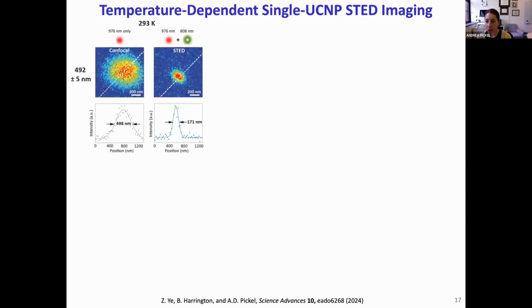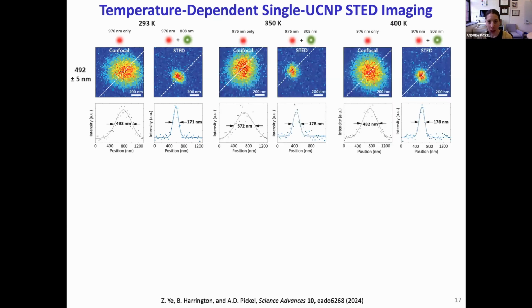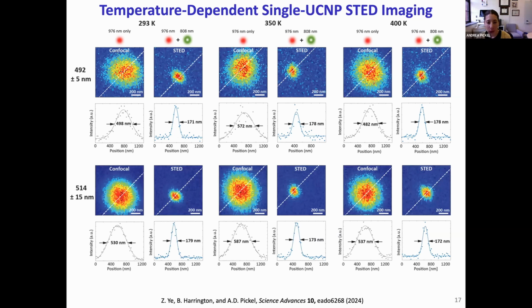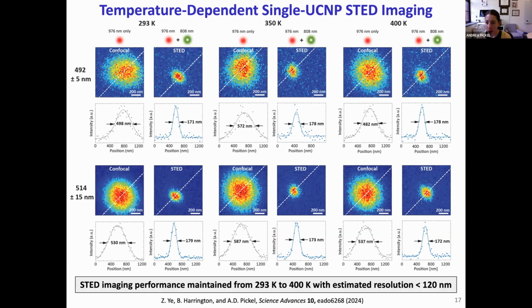From the spectroscopy results I just showed, we now know that we need to test our ability to maintain similar imaging resolution for two of the lower intensity peaks. So we repeated our single UCNP STED imaging, first using the temperature-dependent peak. We maintain a similar level of resolution at room temperature, and likewise at 350 and 400 Kelvin. We then repeat these experiments for the second peak we're interested in, and the results are again essentially identical. In this case, we can use a simple deconvolution to estimate the true imaging resolution, and we find that it's below 120 nanometers for both spectral bands at all temperatures.